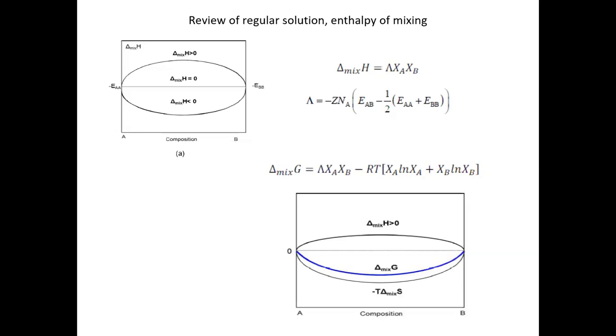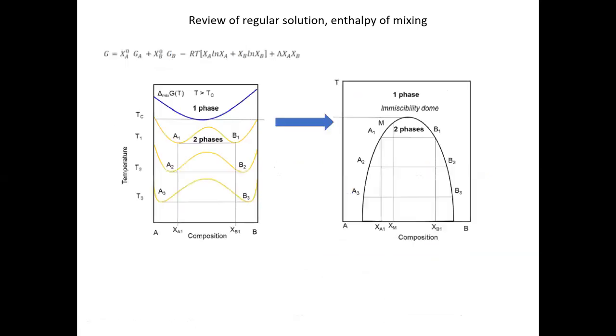But on the other hand, if you have a very high temperature, now the entropy term definitely dominates and you want to mix together. From this very simple analysis, we know that as you change the temperature, you're going to introduce a transition, because you're changing the role of these two competing effects. At high temperature, entropy wins, so the system wants to be mixed together. But as you lower the temperature, eventually enthalpy is going to dominate, and in this case you favor the demixing state. So this basically motivates or drives the spinodal decomposition to occur.